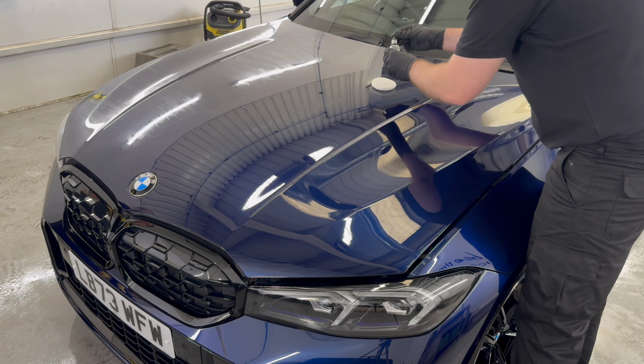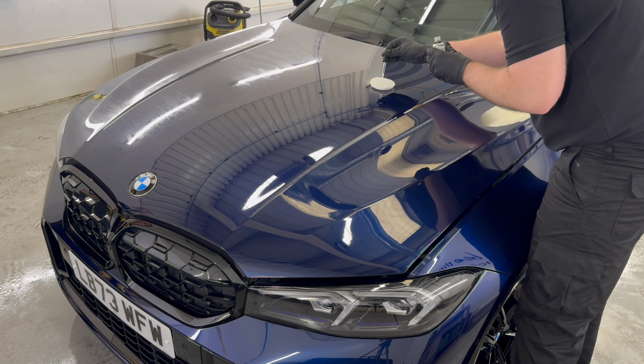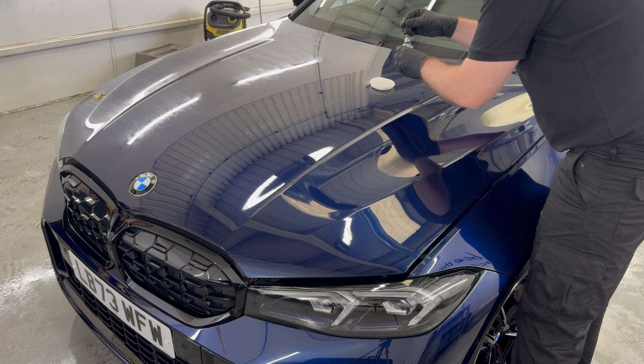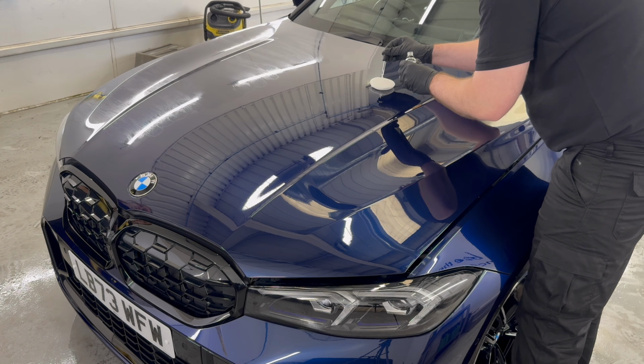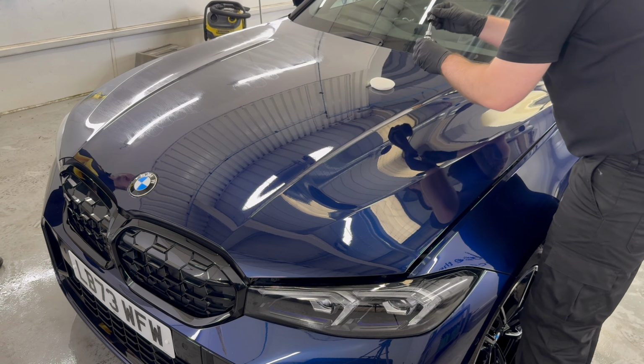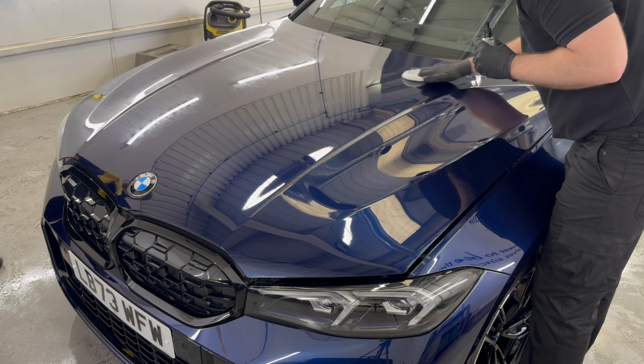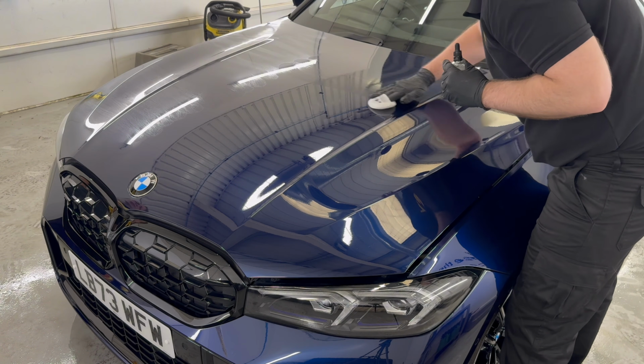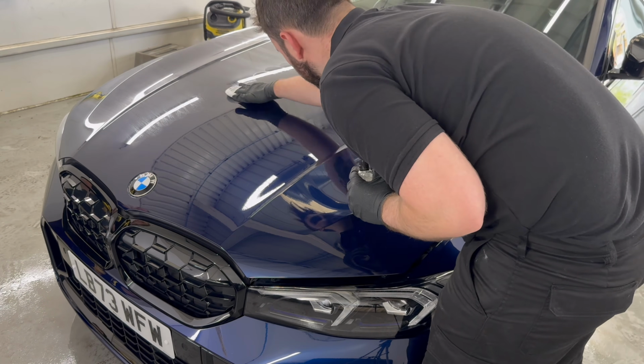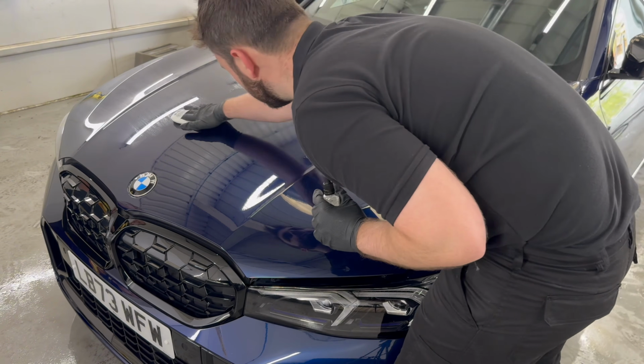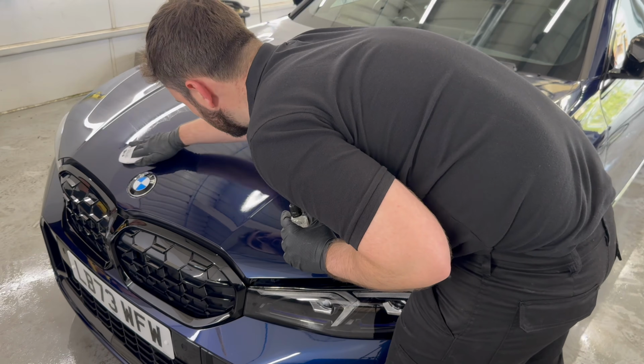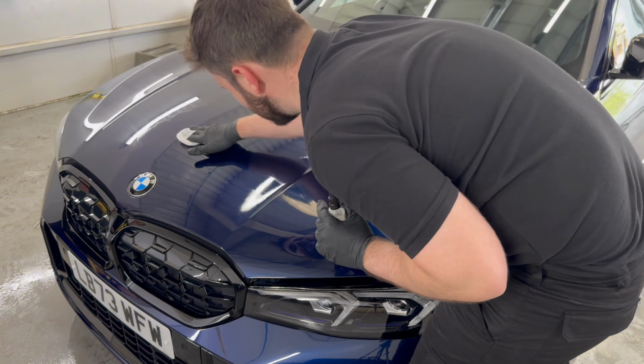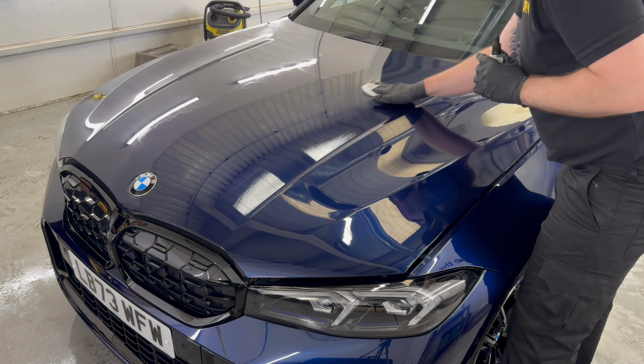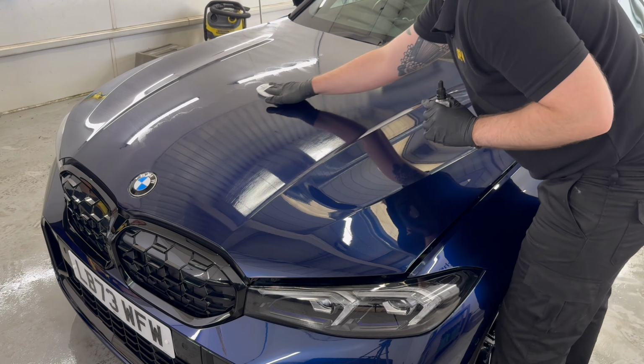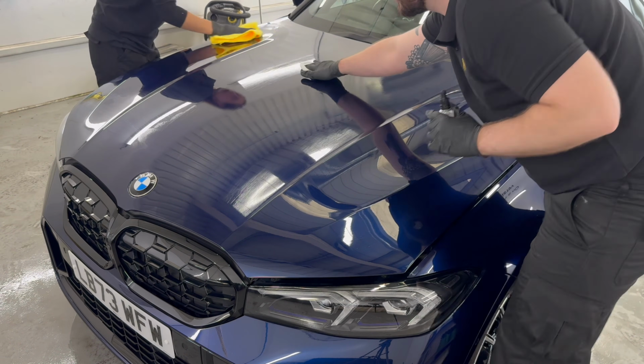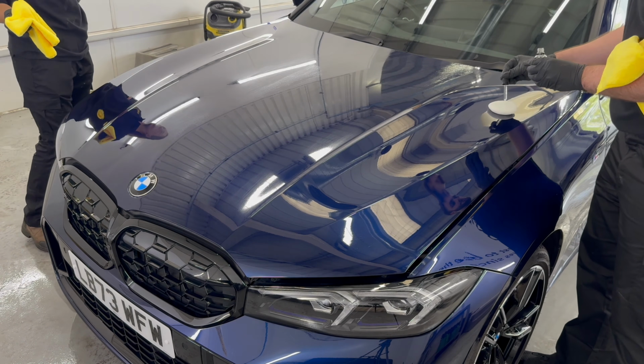If you leave the ceramic coating on the panel to cure for too long, you run the risk of leaving high spots and streaks over the surface of the car. In addition to this, as the ceramic coating cures, you can physically see it turning white or hazy. If you don't remove the flash layer before it starts to turn this colour, the only way to remedy this is to sand it down using the same process as what I was doing for some of the deeper scratches. And by sanding it down, you're essentially removing the ceramic coated layer, and you'd have to start the whole process all over again.